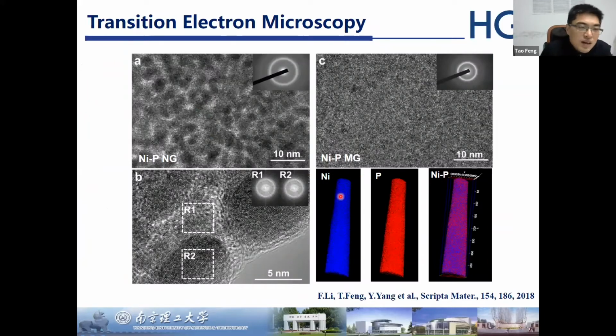More obvious evidence we can obtain from the high resolution TEM. This is the image of the nanoglass. It is clear to see that the nanoglass consists of grain structure and interface. Please notice that all the regions, from the grains and the interface, are amorphous. And there is no obvious chemical segregation from the APT measurement. If you compare with the structure of the metallic glass, you find it has a more uniform structure.